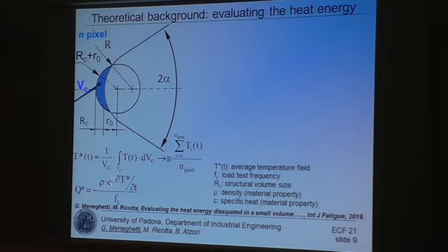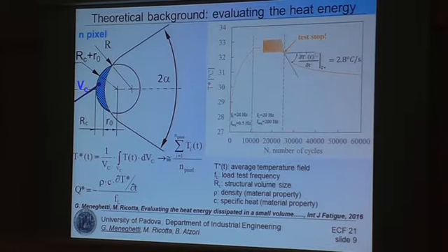So let's go through these equations again, trying to imagine what we have seen in the laboratory. When you start the test, the mean temperature, T star, inside the structural volume tends to rise. When the heat production becomes equal to the thermal heat extraction from the structural volume, the temperature tends to stabilize. Now, suppose you start the infrared acquisition, you see the thermoelastic effect superimposed to the mean temperature level. If you stop the test right here, you measure the thermal gradient, the material cools down, and from this gradient inside this formula, you can estimate the energy dissipated in a unit volume of material per cycle at this point.